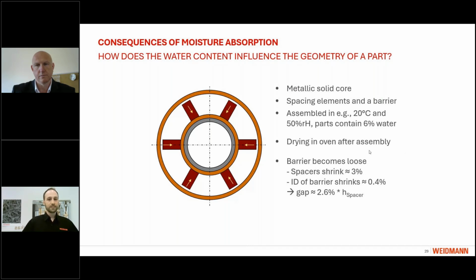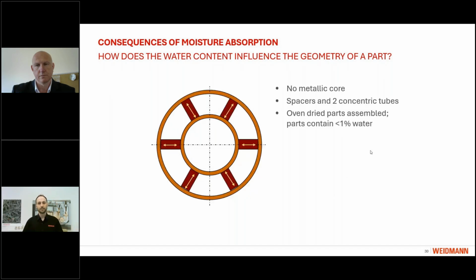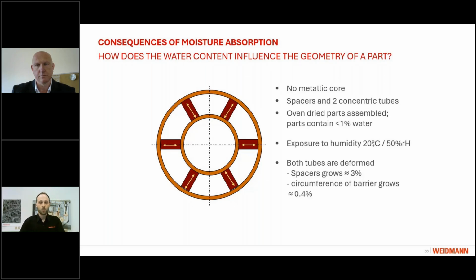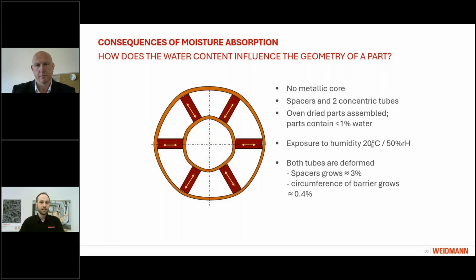The reverse example is we have an oven-dried assembly and we expose that to relative humidity of 50% at 20 degrees. Here we get a swelling, again due to the same reasons, and you can see that now we don't talk about circular shapes anymore. It is really deformed. So when handling material, we have to be aware of these geometrical consequences the material will have by just coming in contact with ambient conditions.